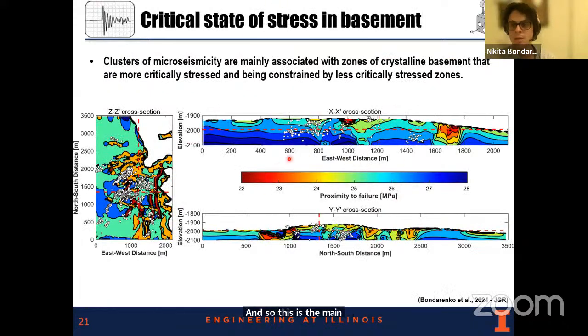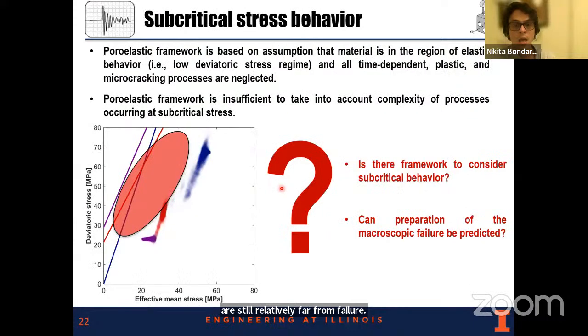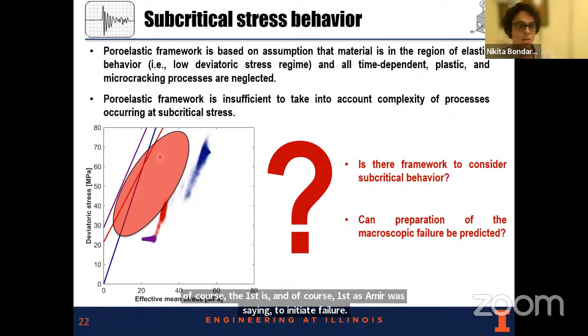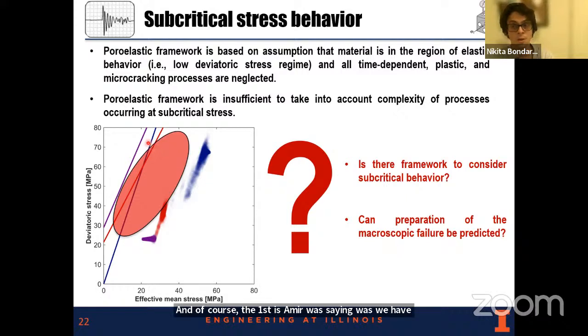We are still relatively far from failure, so we need to change the state of stress significantly to initiate failure. As Amir was saying, we have very significant uncertainty in the state of stress, especially it's challenging to measure the major principal stress. If we underestimate the major principal stress, the whole distribution will be shifted closer to failure.